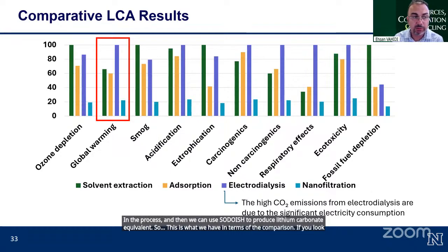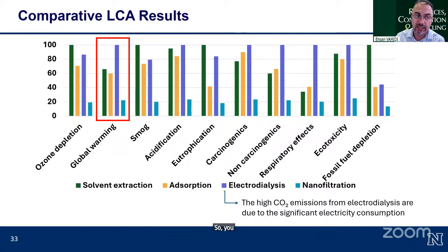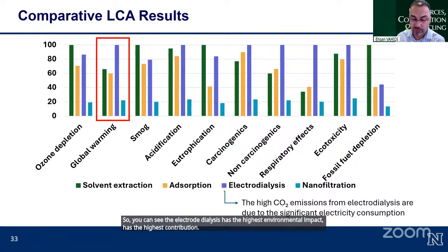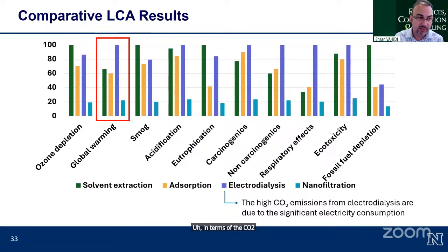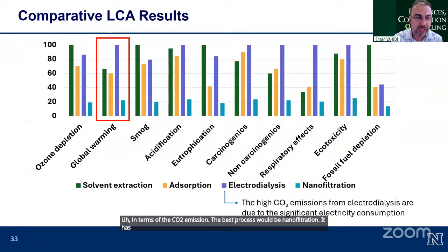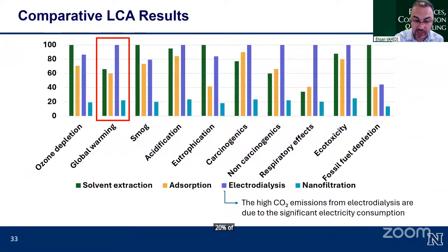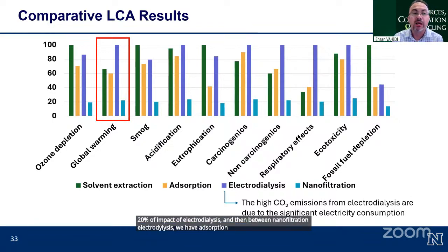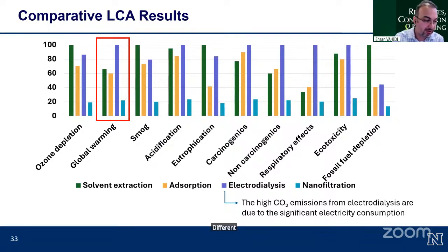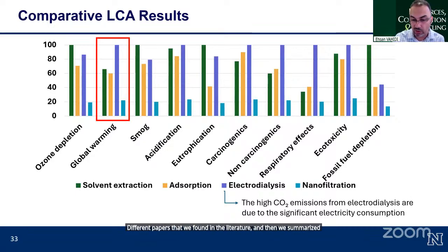If you look at global warming, you can see electrodialysis has the highest environmental impact, the highest contribution in terms of CO2 emission. The best process would be nanofiltration. It has almost 20% of the impact of electrodialysis. Between nanofiltration and electrodialysis, we have adsorption and solvent extraction. All the results are based on different papers that we found in the literature, and then we summarized and synthesized those results from the papers